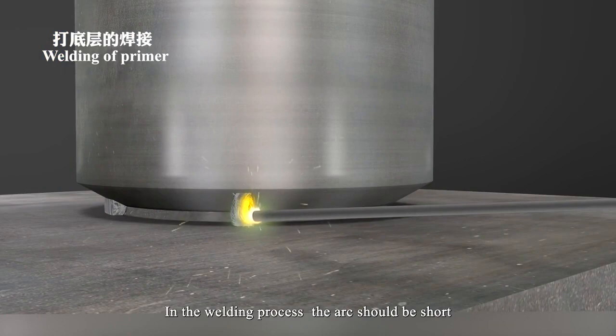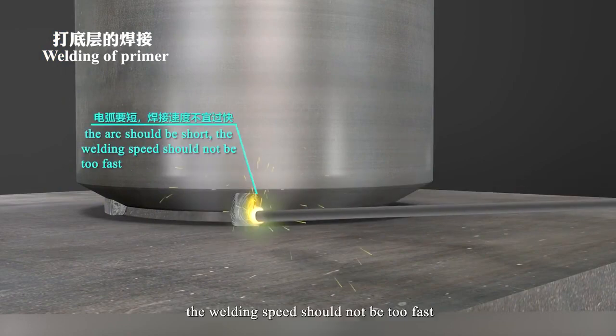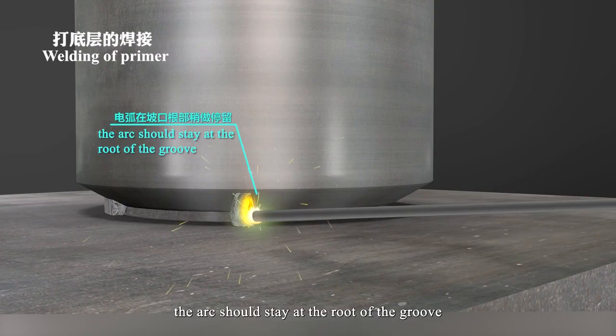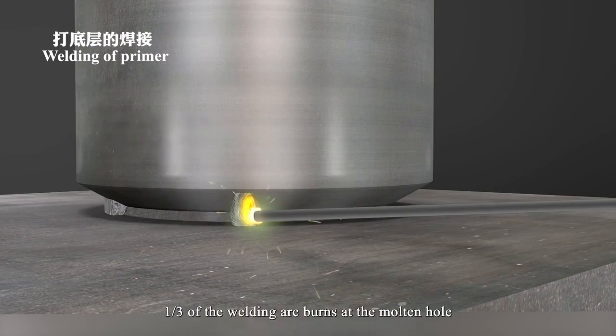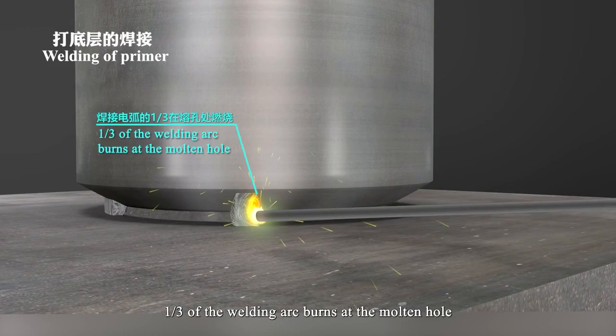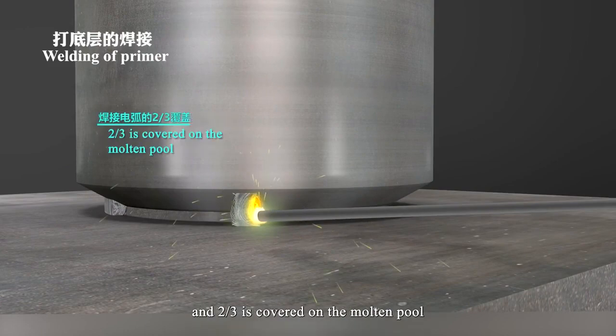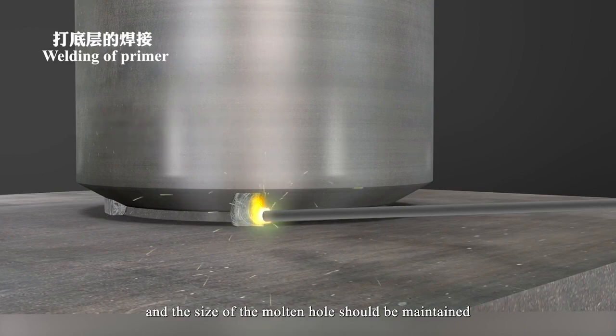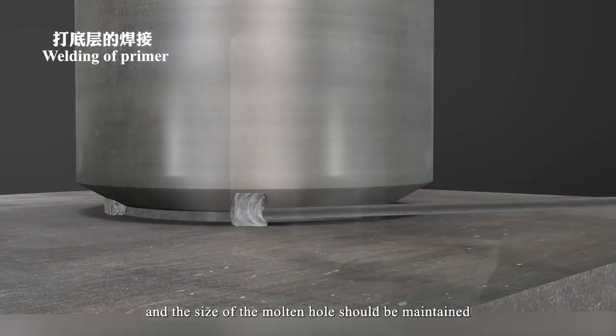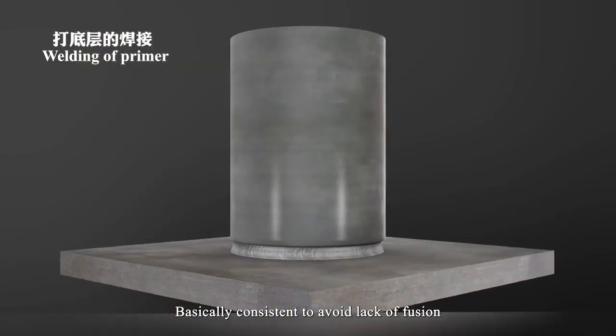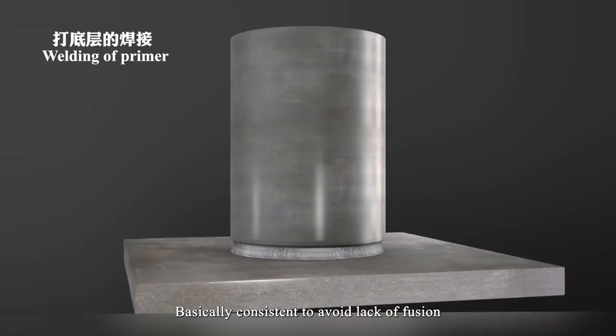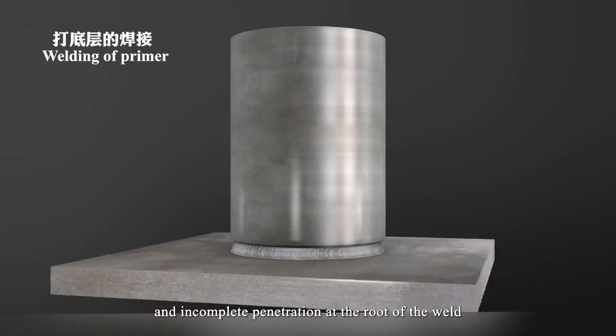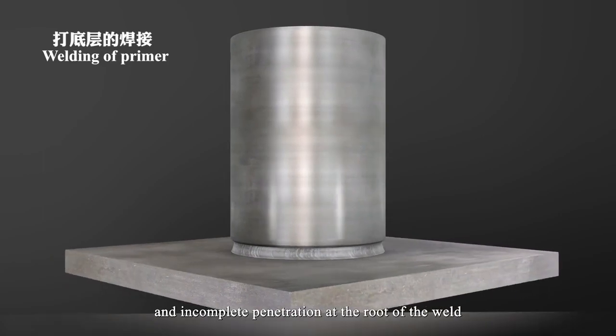In the welding process, the arc should be short. The welding speed should not be too fast. The arc should stay at the root of the groove. 1/3 of the welding arc burns at the molten hole, and 2/3 is covered by the molten pool, and the size of the molten hole should be maintained basically consistent to avoid lack of fusion and incomplete penetration at the root of the weld.